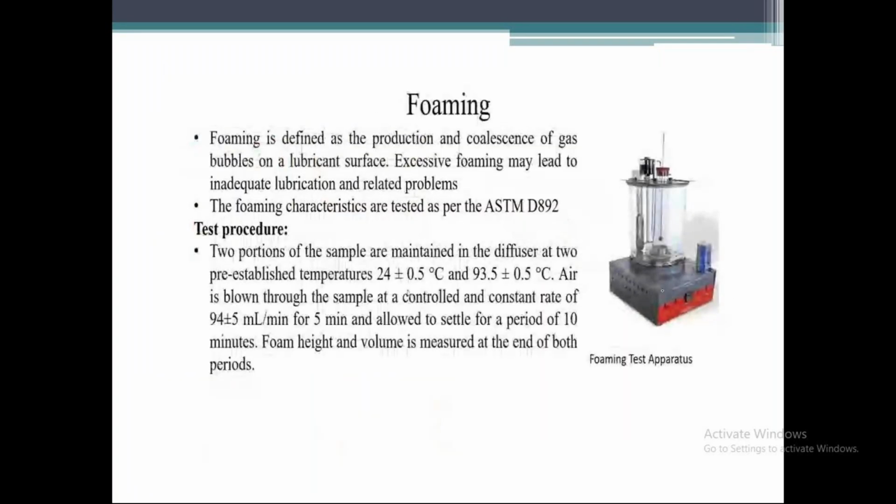I'm just skipping that. Foaming is how many bubbles form. It is not good for a lubricant if more bubbles form during operation. For that, we artificially create a situation where we purge gas through these tubes, and we see how much bubble gets formed with respect to this standard. Again, these are with respect to different conditions. The temperature should be maintained, and we have to measure how much height the foam has reached. That is the measure of foaming.